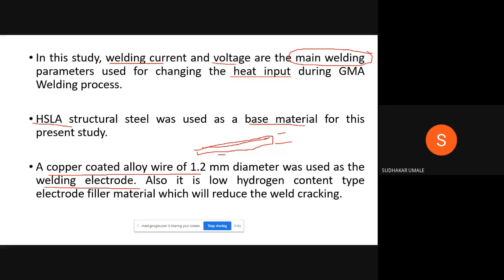As you observe, a low hydrogen content type electrode filler material reduces the weld cracking. So let us say if the weld metal consists of hydrogen, by chance hydrogen is added in the weld material, we have very, very slow cracking. So this slow cracking is called hydrogen cracking. And hence we are taking care of that. So zero hydrogen is added into the system. If some hydrogen is added, definitely you are getting the slow crack. It is not visible during the welding, but definitely there is cracking that is called hydrogen cracking. And our aim is to reduce the hydrogen cracking, which reduces the strength of the welded joint.